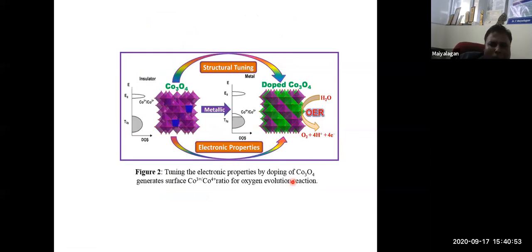You can take any material, dope it and tune it, through structural tuning and also electronic properties, and vary the density of states. This is like an insulator. When you want to make it metallic, you just dope the cobalt oxide, and it becomes metallic. What happens for OER is that when you dope with something like nickel or lithium, it increases the 3+ to 4+ ratio. Normal cobalt oxide has 2+ and 3+. When you dope it, the 3+ to 4+ ratio increases, which is better for oxygen evolution reactions.